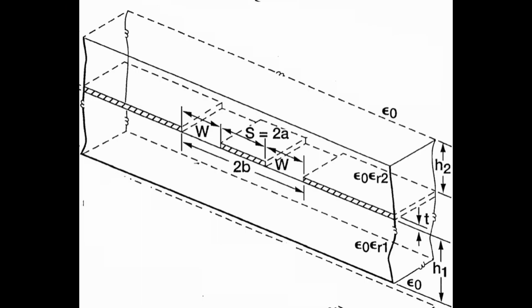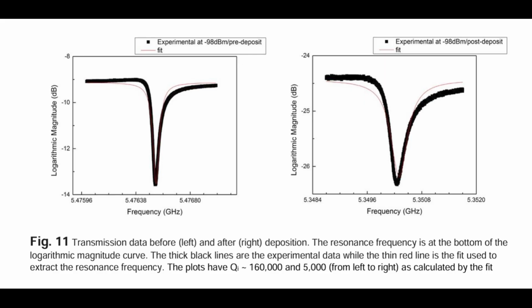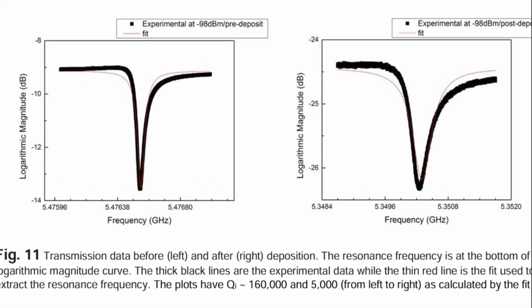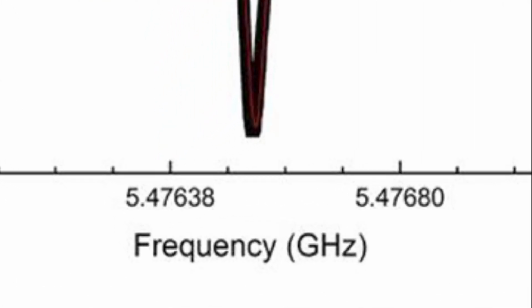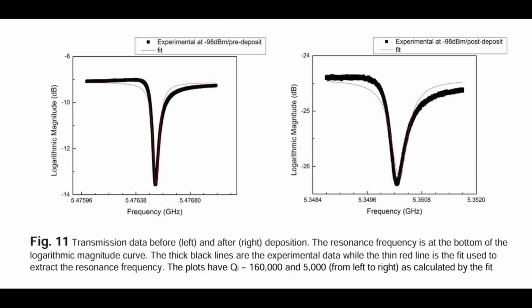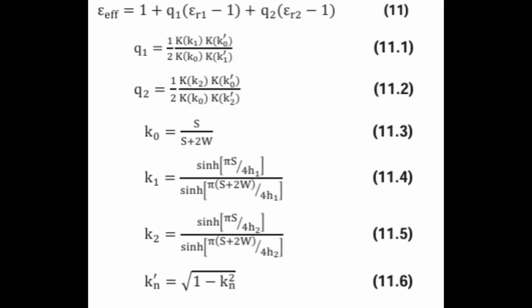The CPW can be modeled as a superconducting circuit sitting on top of a substrate H1, in this case silicon, with the material H2 being the effective dielectric contributor on top. As you can see with this diagram, by adding the material, the effective resonance frequency of the resonating cavity is shifted. This is because essentially the speed of light, or the effective dielectric of the circuit, is changed, causing a resonant frequency shift. It's through this resonant frequency shift that we can determine the new effective dielectric of this material through these equations. The effective dielectric is given above, where Q1 and Q2 are the filling factors, or how much energy is located in each dielectric source, whether it be the material on top or the silicon on bottom.